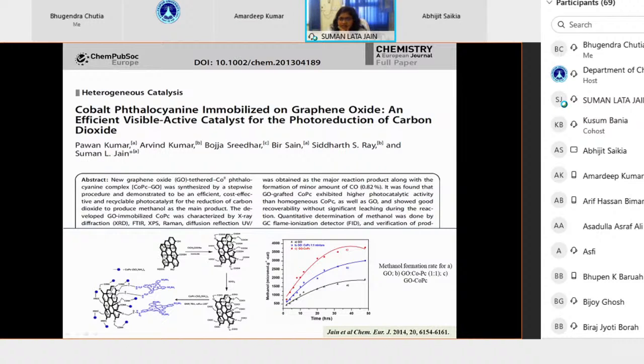Here we use graphene oxide as the semiconducting support. In some of the literature, graphene oxide is known as a visible light active material. So we have chosen this photoactive support for effective immobilization or chemical attachment of the complex. Firstly, we functionalize the graphene oxide with chloroacetic acid to enhance the carboxylated functionalities on it. After that, it was treated with our complex, cobalt phthalocyanine tetrasulfonamide, to get this hybrid system. In this hybrid system, the chemical attachment of the complex with our photoactive support not only provided stability but also provided a direct connection between the support and the complex.